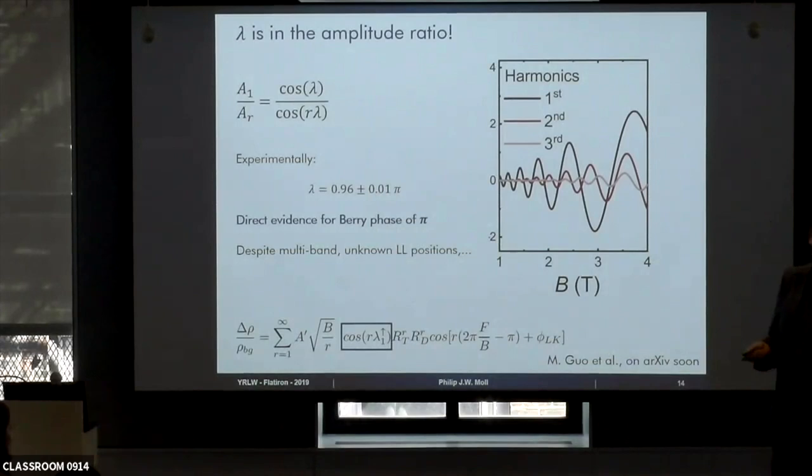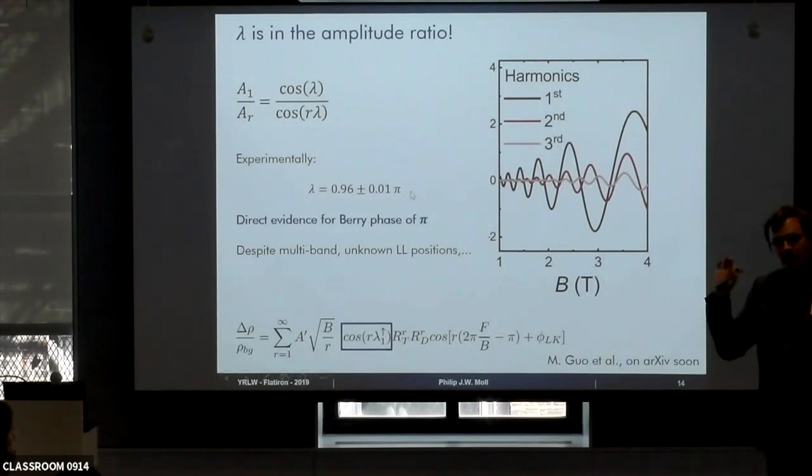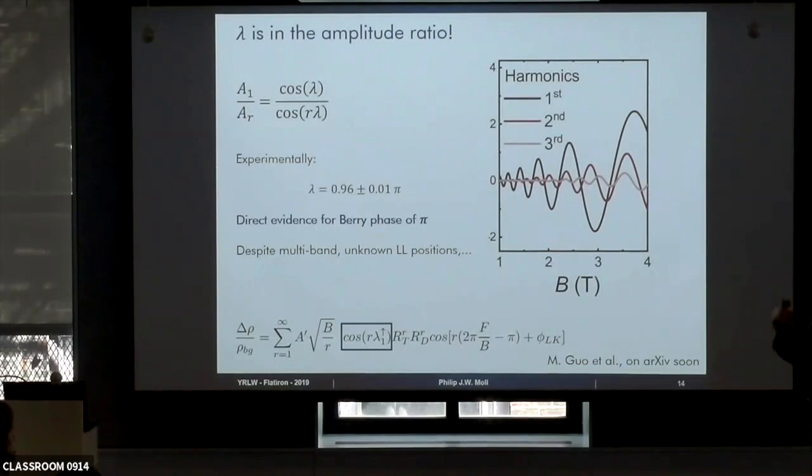I don't want to walk you through all of that, but the point is here, with an analysis like this, you can maybe not prove, but have very strong evidence for a Dirac pocket, even though you're stuck in huge metallic bands. And a key point there is that the analysis relies on the smallness of the Hall effect. So the huge metallic bands actually help you a lot, because they quench your Hall effect, or reduce the Hall constant.